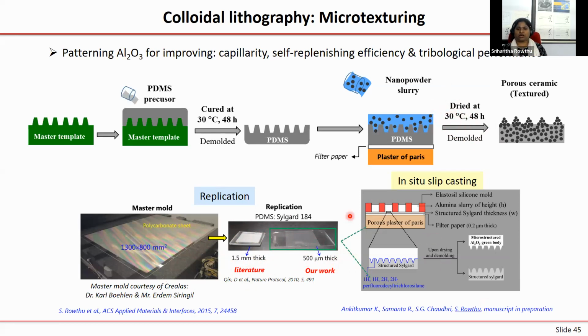Now this is the so-called in situ slip casting, or you could also call it colloidal lithography. Now this PDMS is textured. Remember, this particular region here is textured, and this is not textured. Similarly here, this is not textured, while the middle part is textured. So on this textured region, if you simply pour a very little amount of alumina slurry, then you are more or less going to make it like a coating.